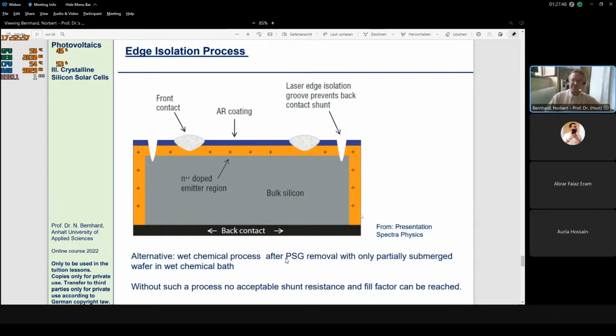The second possibility would be that we use again a wet chemical bath process, and we would use this after PSG removal. If you remember, after the doping, we had this PSG removal. We could have a second wet chemical process with the wafer just half submerged and just removing the doping on one half of the wafer. And this, of course, again would interrupt this shunt to the backside. If we wouldn't do this process, this solar cell would have a very bad fill factor and a very poor performance.